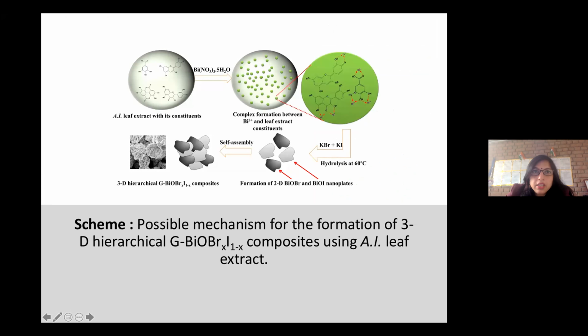So this mechanism was given. This is the leaf extract and its constituent, anthocyanin, and all constituents. Then this forms the complex between bismuth ion and leaf extract. Here we showed that when the KBr and KI precursors were added, BiOBr and BiOI nanoplates formed, and by a self-assembly process, this hierarchical structure was formed.